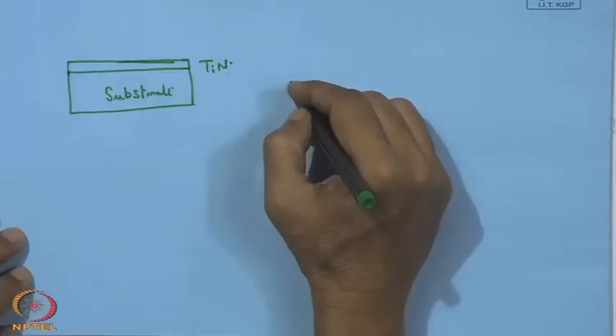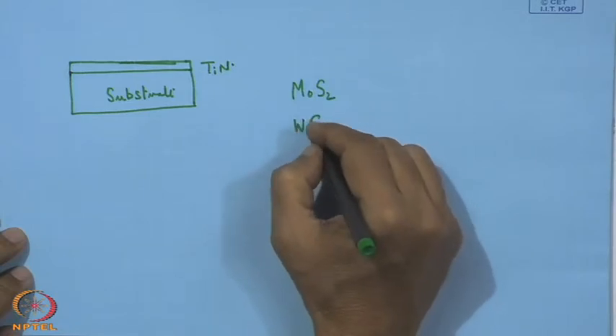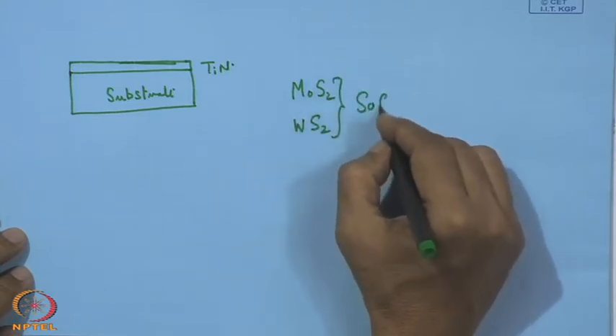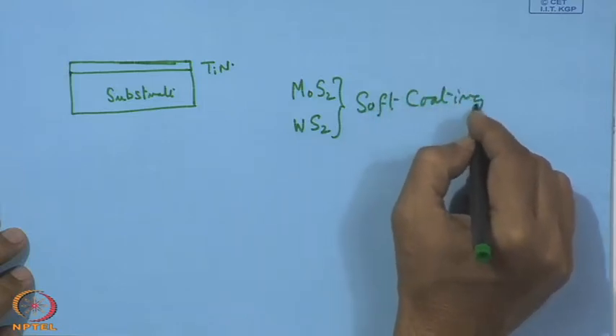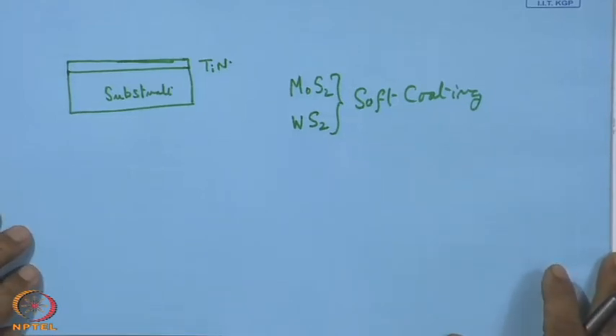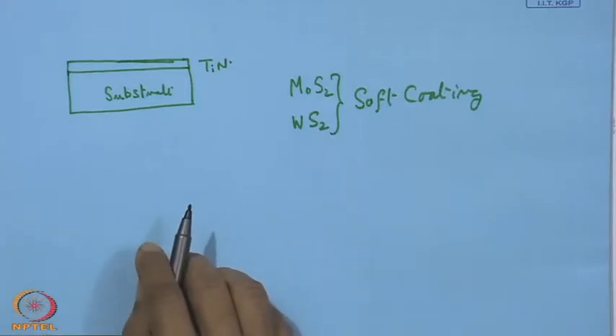We know that we call them super lubricious coating, but at the same time this MoS2 or WS2, we also call them soft coating. So, we have actually two extremities, ultra hard coating, hard coating, and this is soft coating. So, that is a wide range. On one side we have diamond, CBN, those are ultra hard material. In between we have all hard material, that means conventional hard material, say for example, all carbide, nitride, boride of transitional element. We have aluminum, silicon, their nitride or oxides, that can be also mentioned. However, on this extremity, we have a soft coating of MoS2 and tungsten disulfide.